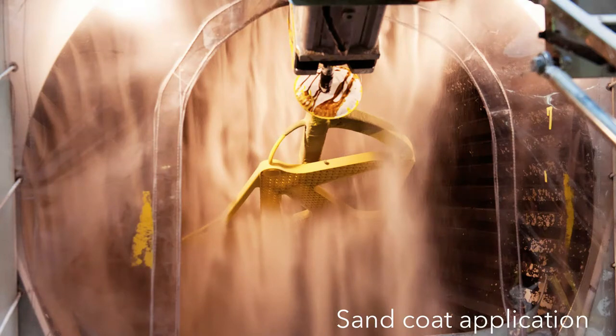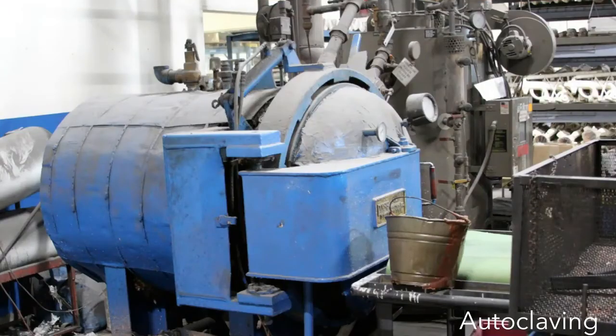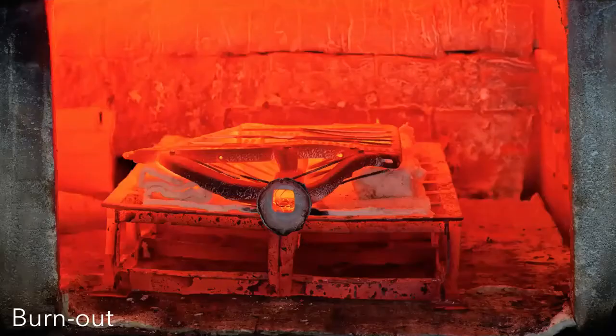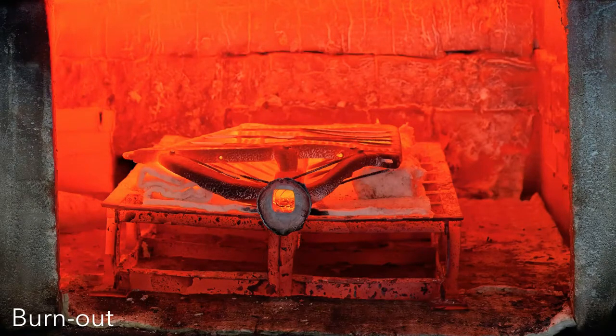Once you've built up your molds, you autoclave it, and that melts out the wax so that there's less material combusting during the next stage, which is burnout, where you actually vitrify that ceramic shell to strengthen it and vaporize out any residual material. So it's worth noting there are a lot of different types of materials that can be used for pattern materials, even PLA from desktop 3D printers. We actually did a lot of early work just using $2,000 MakerBots and printing patterns, and we're able to get some very nice parts that way.